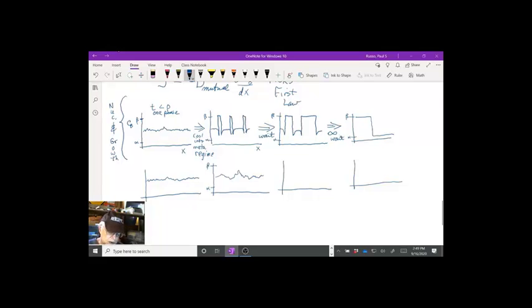And then what you start having is, let's just say that the sine wave is this way, and it starts growing like that. And what's kind of amazing about this is that if I'm a molecule down here at this particular value of x, so take a particular value of x here, and I'm a molecule there, I actually climb up the concentration to make that nucleus form, to make that new phase form. I actually get to diffuse up.